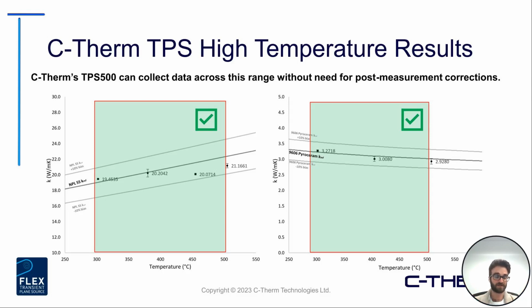We are able to get really good, consistent data within the expected tolerance window across that range, and there is no post-measurement correction or additional work required. This is all just directly measured from the sensor at high temperature. So it's been something that groups have pointed out. If you are needing high temperature data, in that 200, 300, 400, 500 degrees C range, really a great solution is available for you with the TPS 500. So definitely feel free to reach out if that's of interest.